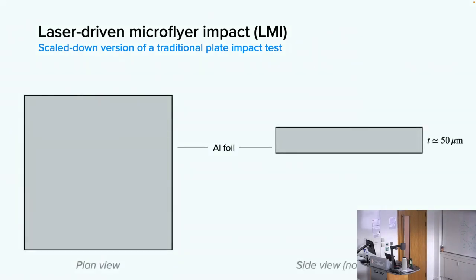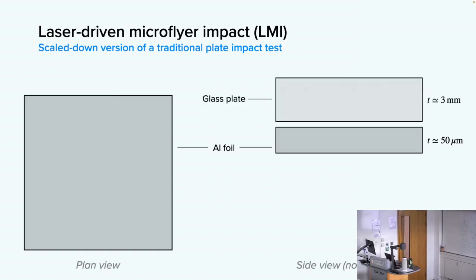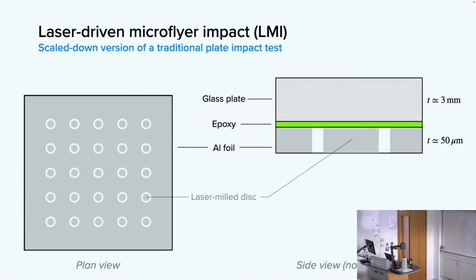So our flyer now is going to be a piece of aluminum foil. Here's a plan view of an ordinary piece of aluminum foil. Here's the side view. Maybe it's 50 microns thick, approximately. I'm going to take that piece of aluminum foil and a glass plate, and I'm going to glue them together with some epoxy. Before I stack it, I'm going to take a laser and mill out a bunch of discs in that aluminum foil. And these discs now are going to be our little flyers.